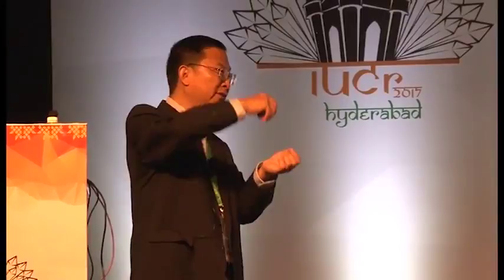For dysprosium, for erbium, and for transition metal. First thing, we should choose spin carriers, the magnetic center. And here we choose lanthanide and some transition metals, and the orbital contribution is most important for the easy axis, for the anisotropy of the molecules. Second, the coordination bond, for example, dysprosium and the ligand, or cobalt with nitrogen, some short, strong magnetic ligand bond. In some cases, actually, it's directing the easy axis.